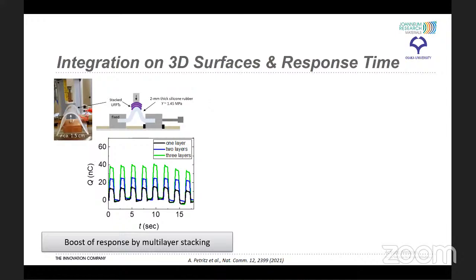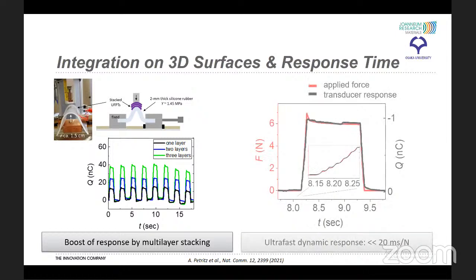The ultra-small sensor thickness allowed us also to stack multiple sensors on one another and thus further multiply the sensor response. And we can do that also on a 3D shaped object like this pre-bent silicone rubber. So for 3 sensors stacked, we get a 3-fold increase in the charge response. Moreover, the superior sensor performance is also reflected in an ultra-fast dynamic response, where we have less than 20 milliseconds per Newton response time. And accordingly, the shapes of force excitation and charge response characteristics are nearly identical.